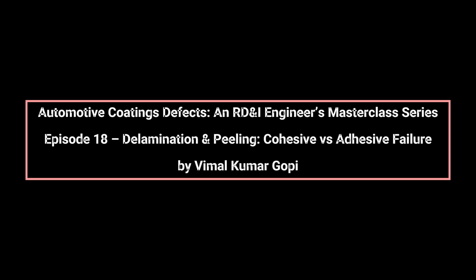Environmental exposure accelerates both adhesive and cohesive failures. Moisture penetrates weak interfaces, reducing adhesion through hydrolysis or osmotic pressure. Temperature cycling amplifies expansion mismatch between substrate and coating. Stone impact creates microcracks that propagate along weak planes. Delamination often begins at these microfailures long before it becomes visible. This is why many failures appear suddenly in the field despite years of acceptable lab testing.